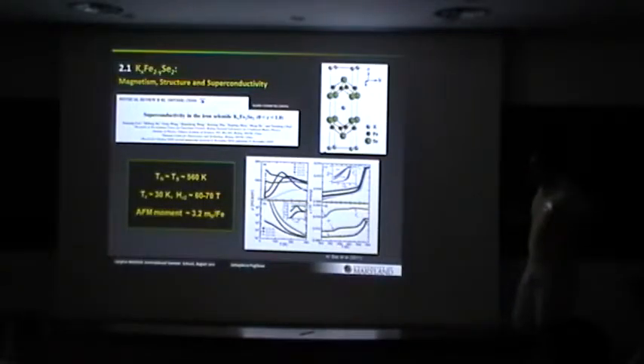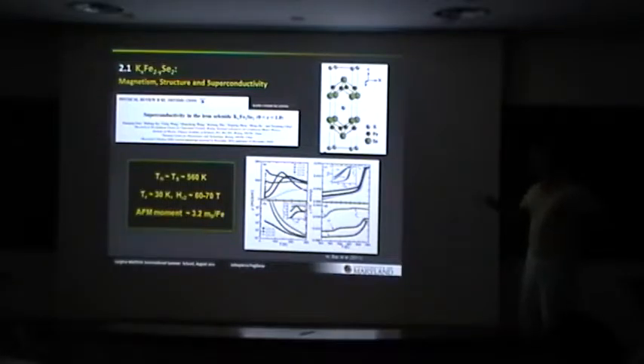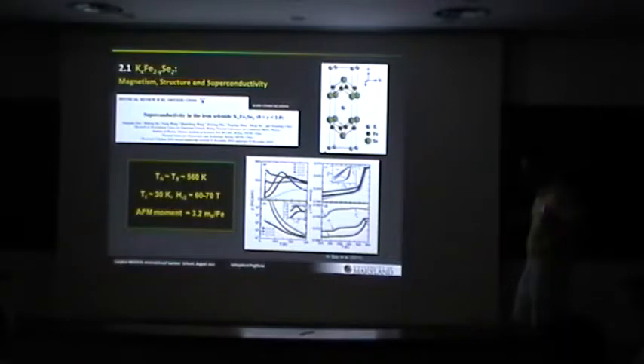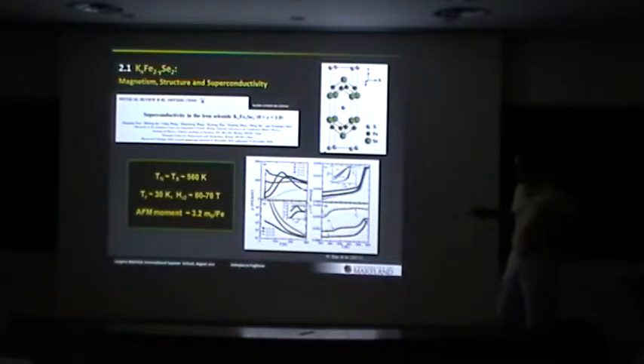Before I get into that, though, there are some very peculiar properties of this compound. In particular, there's good evidence, and I'll show it, of magnetic order that onsets at almost 600 Kelvin. And that magnetic order has quite a large moment. Actually, it's much larger than the staggered moments seen in all the other iron-based superconducting compounds. And it has a superconducting transition of 30 Kelvin. So this is quite a unique material. Now, you can see in this slide, this is just a summary. As you change the chemistry of this compound, you can get everything from what I would call insulating behavior, on a log scale in resistivity, to some weird downturn, to relatively low resistivity with a superconducting transition. So, in general, this material is very sensitive to the chemistry. We'll go into that a little bit more.